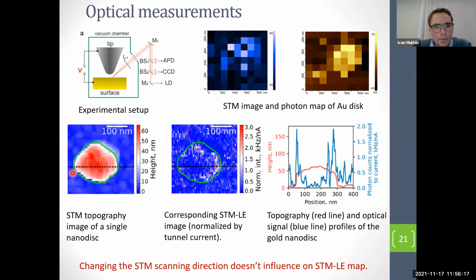Good. When we improve the resolution of imaging, this is again a single nano-antenna. This is the STM topography, and this one is the simultaneously acquired optical image associated with photon generation. And you clearly see that the periphery of this disk emits more light. To make this clear, you can have a look at the profile of this STM and optical map image. The red curve shows the nanodisk position, and the blue lines show the optical signals. It's quite clear that at the edge, at the periphery of our nanodisk, we have enhanced optical emission.